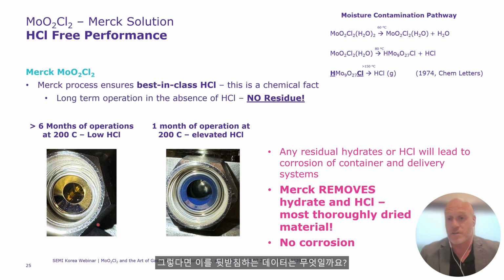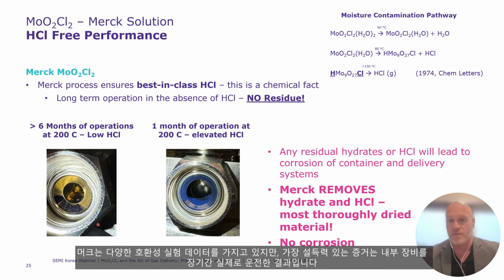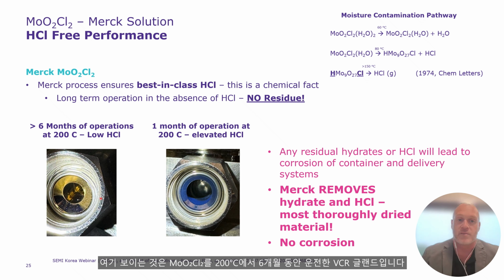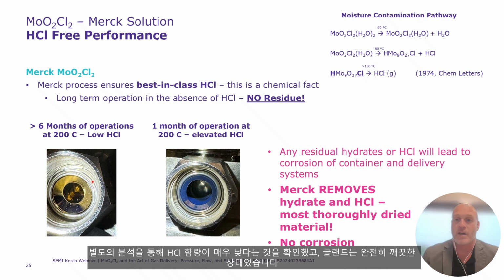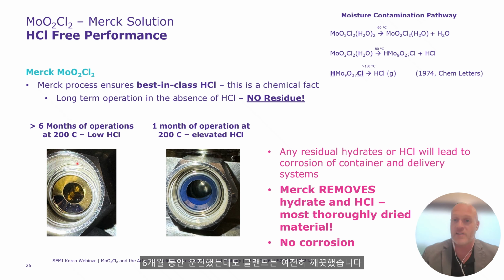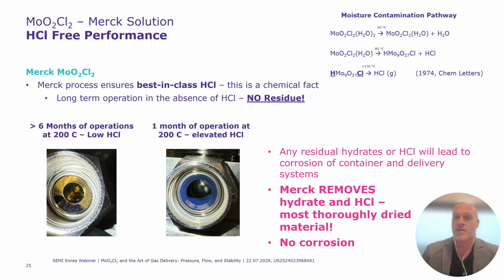And so what data do we have to support this? We have a mountain of different compatibility studies, but I think the most compelling evidence is our equipment internally that we've operated for long periods of time. What you're seeing here is a VCR gland that's been under operation with high temperature moly dioxide dichloride, 200 degrees C, for 6 months. We've confirmed via separate analysis that the HCl of this material is low. And this gland is spotless. After 6 months of operation, this gland is spotless.